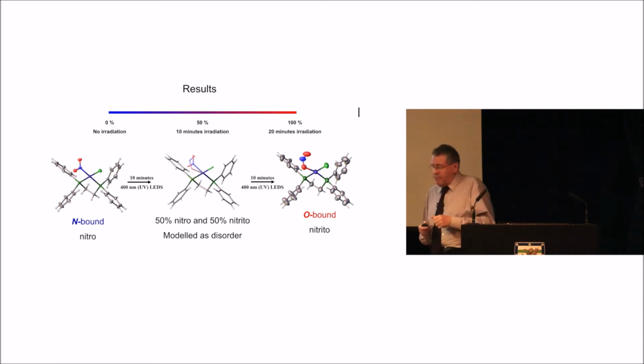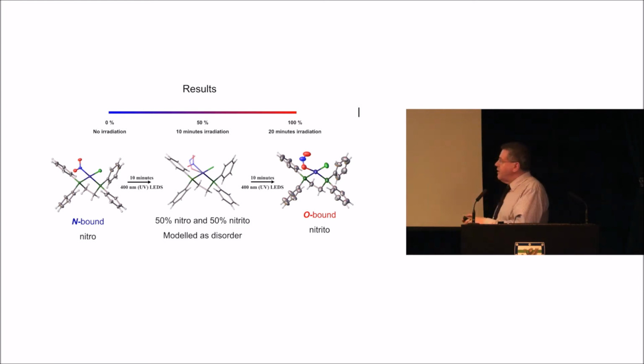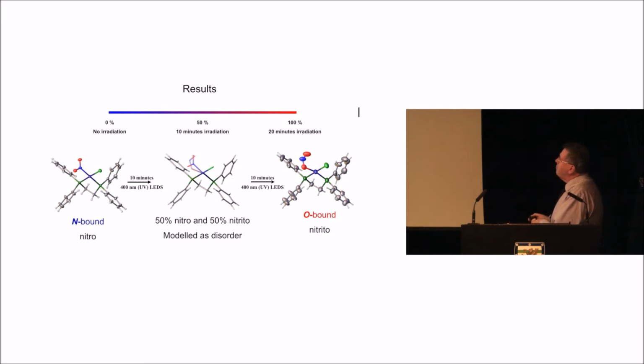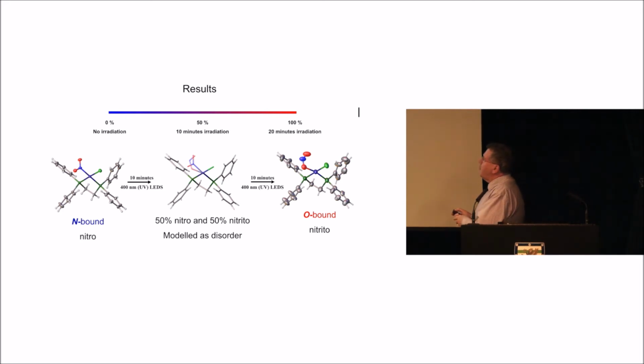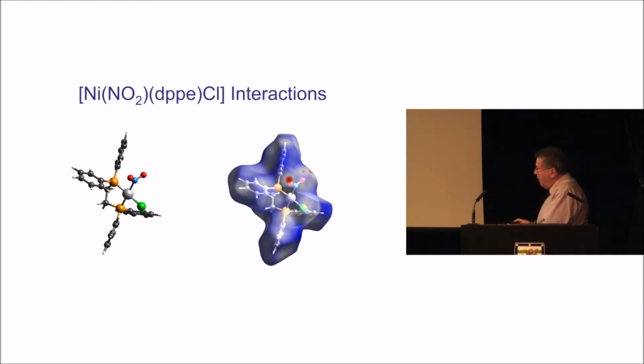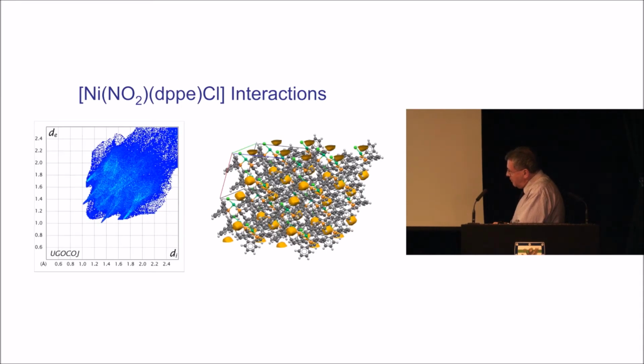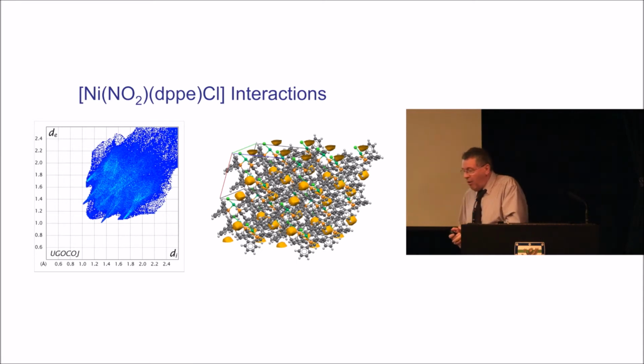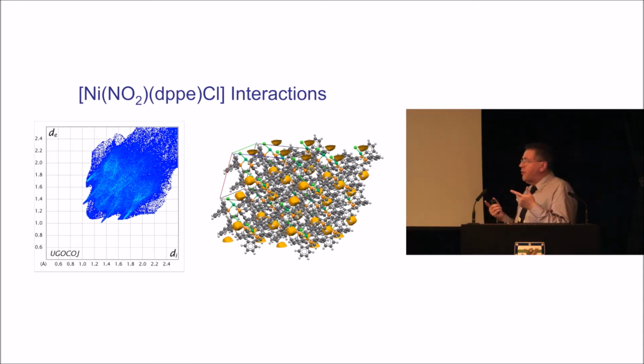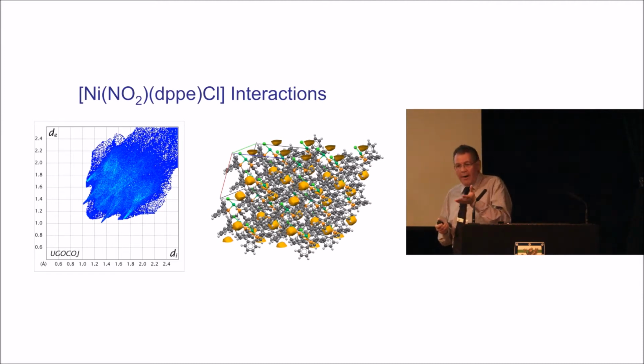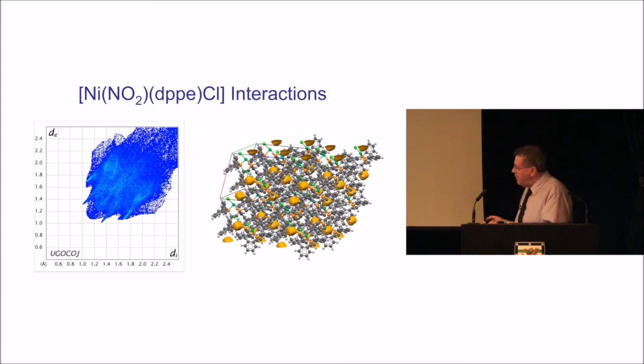And if we look at the structure, you can actually see there are some hydrogen bonds. The NO2 oxygens are acting as hydrogen bond acceptors, but not terribly strong. And if you look at the fingerprint map, which illustrates whether or not there are hydrogen bonds, you can see that these little sharp peaks suggest that there are, but they're not particularly strong. And as Jack says, atoms have got to be somewhere, so not a particularly strong interaction.